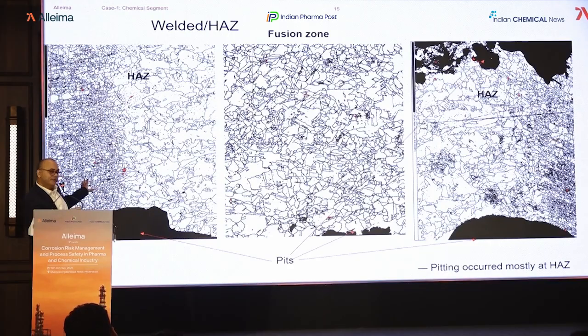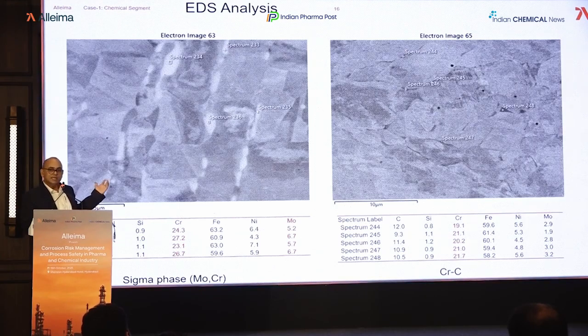You can see that there's a variation in the microstructure. That suggests there is some temperature gradient. If you go from the fusion zone to the heat affected zone, then the base metal, you have a temperature gradient. When you go from the fusion zone to the heat affected zone, temperature varies from 400 to 800, and in that region there's a chance of intermetallic phase formation. So we used the EDS that I have shown you to see what phases are forming.